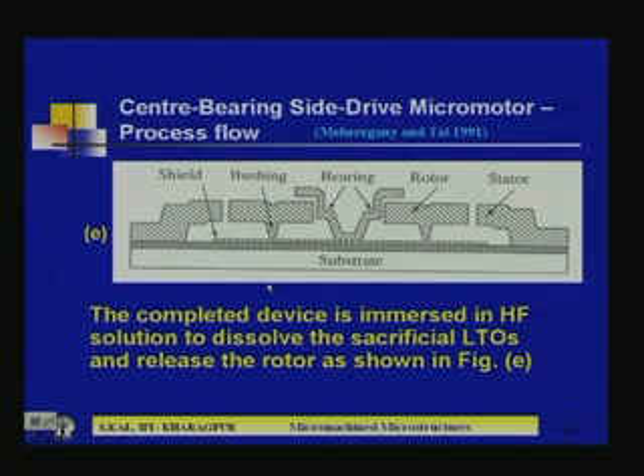The completed device is immersed in hydrofluoric acid solution to dissolve all the sacrificial LTOs and release the rotor as shown in figure E. So, this is the step by step. You have to give a little bit of concentration on each step, how the structure is formed by subsequent lithography and etching to get the ultimate structure. That is a side drive micromotor, and that picture you see in many of the MEMS articles, the electrically driven micromotors using the MEMS surface micromachining technology. These are the process steps we use for getting such structures.